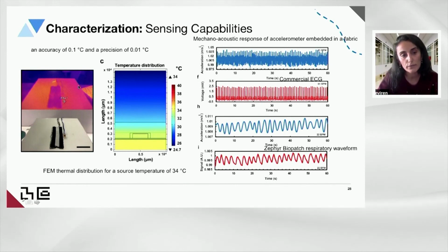And you can see from this top image, it's an IR image where we have the electronics underneath on the hot plate, and we increase the hot plate up to 34 degrees Celsius, and we can find our sensor accuracy almost 0.1 degrees Celsius and precision of 0.01 degrees Celsius. And we also did FEM simulation to show that experimental results match well with the theoretical results.